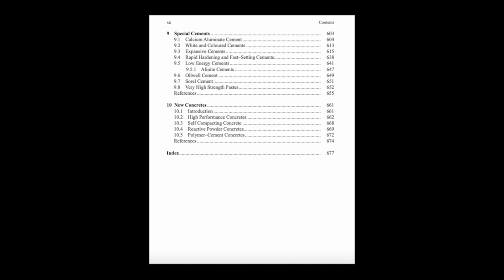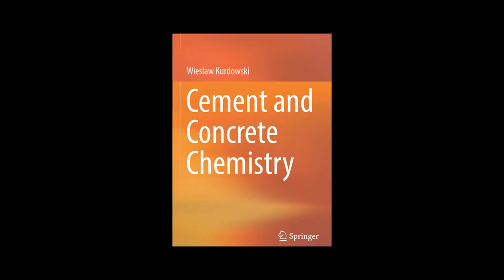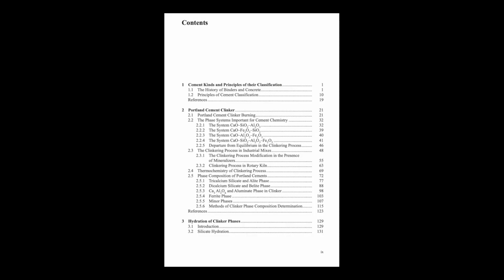Why? What's the mechanism there? Primarily two things. It can potentially decrease the pH of the pore solution, making the environment less protective for steel. And the other? It significantly increases the electrical conductivity of the pore solution because of the chloride ions. That facilitates the whole electrochemical corrosion process. So even if some chloride gets bound up in the CSH. A substantial amount often remains soluble in the pore water, free to migrate to the steel and cause corrosion. That's why standards strictly limit chloride content. So acceleration, but at a potentially high cost to durability.